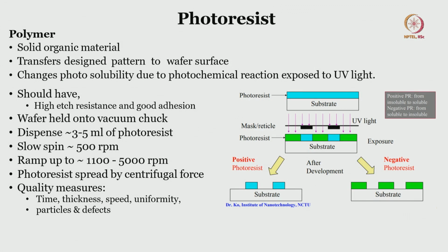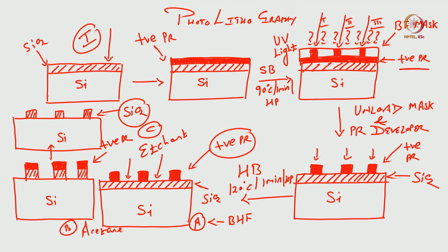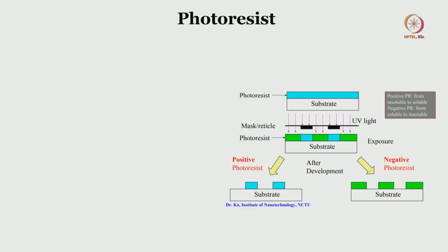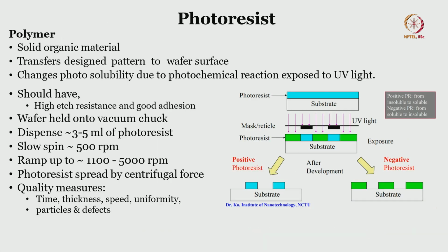What should be the parameters of the photoresist? So, it should have a high etch resistance, good adhesion. What is high etch resistance? So, let us go back to the slide which is here. Now, we see here the photoresist when it is dipped in the buffered hydrofluoric acid. So, when you take this wafer A and dip in buffered hydrofluoric acid, the photoresist is not getting affected. You see, the photoresist is intact, only the silicon dioxide is etched, right. So, it should have high etch resistance, that is what high etch resistance means, and good adhesion to the wafer.